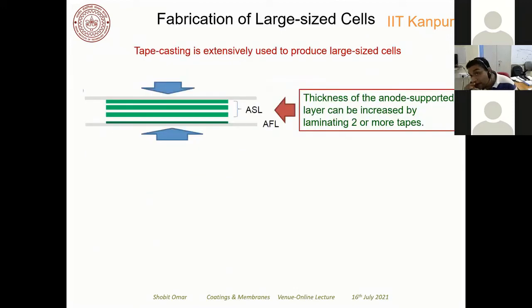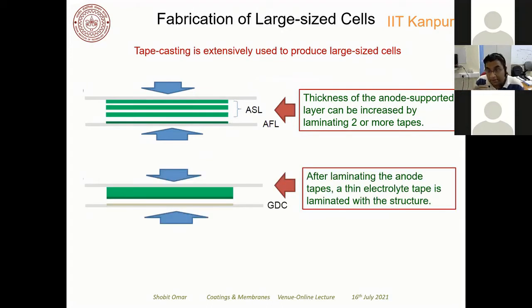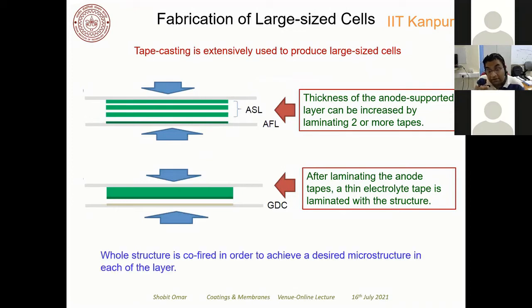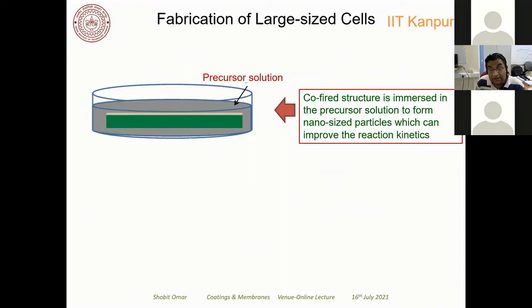And if you make a large scale cell, then you have to use a lamination process where you laminate the tapes together, right? So this is the lamination process where you are laminating different tapes together, thick film and thin film. And sometimes you also have to infiltrate some precursor solution in the cathode and anode in order to enhance the catalytic activity of the electrochemical reaction occurring at the electrodes.